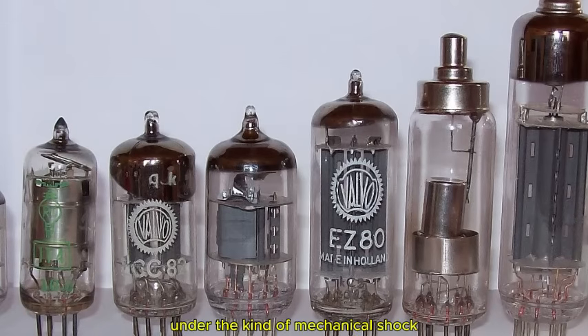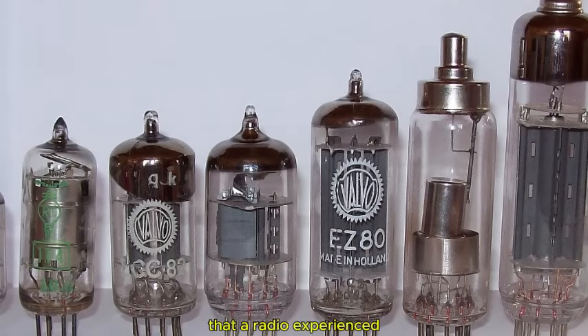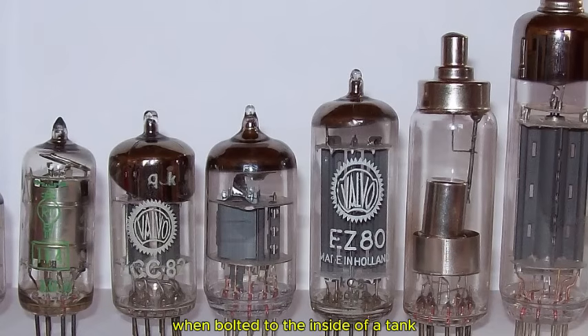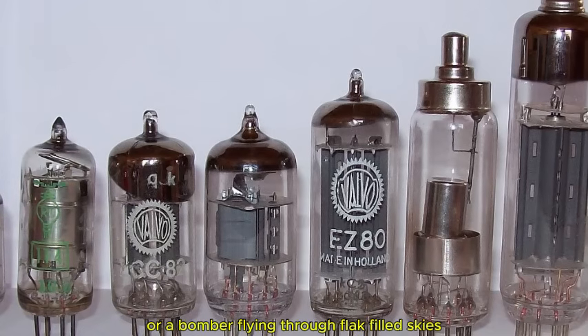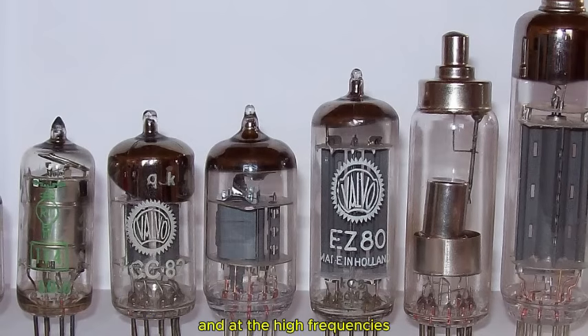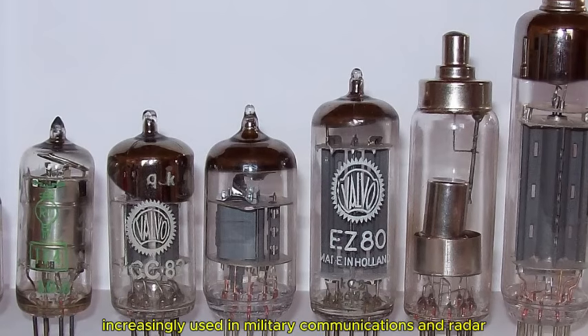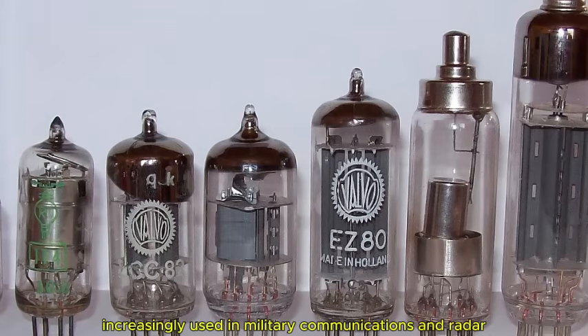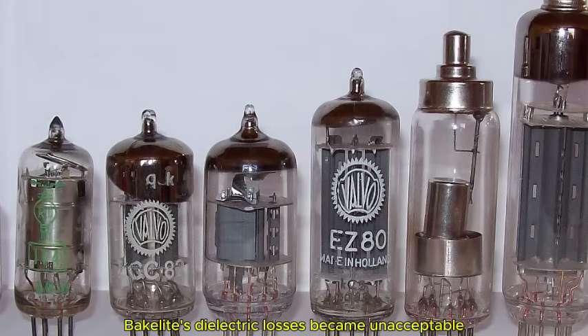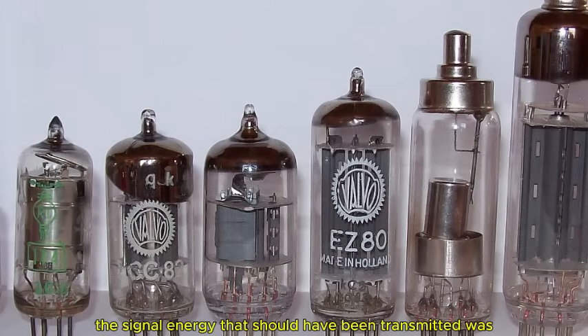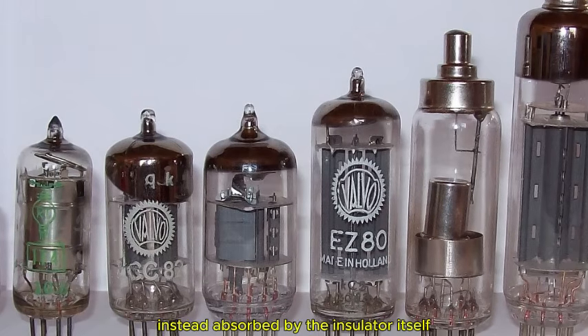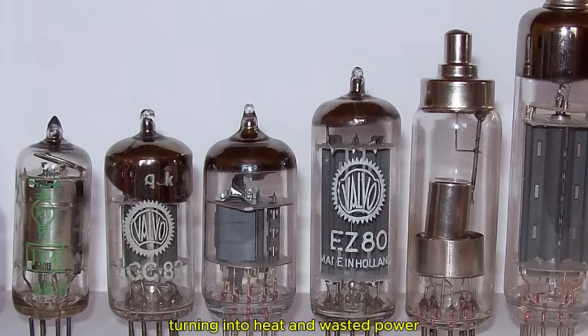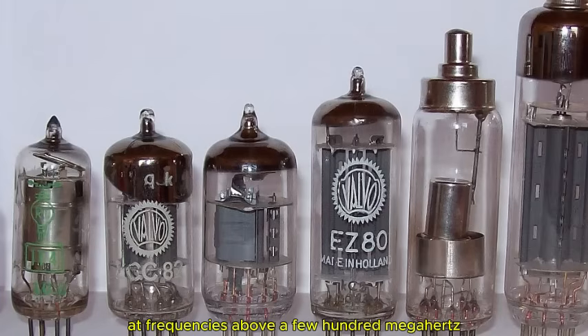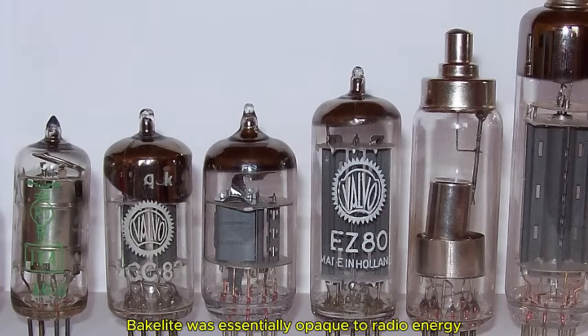Bakelite also cracked under the kind of mechanical shock that a radio experienced when bolted to the inside of a tank crossing rough terrain or a bomber flying through flak-filled skies. And at the high frequencies increasingly used in military communications and radar, bakelite's dielectric losses became unacceptable. The signal energy that should have been transmitted was instead absorbed by the insulator itself, turning into heat and wasted power. At frequencies above a few hundred megahertz, bakelite was essentially opaque to radio energy. The military needed something better.